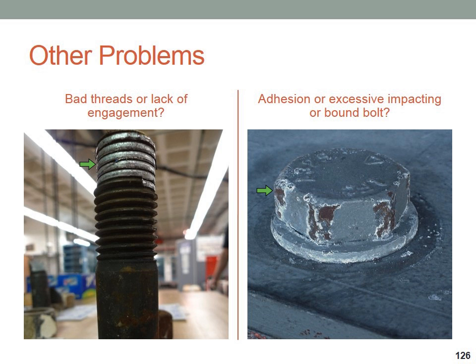One time we had a problem brought to our attention, wondering if the zinc was properly adhering. We actually found out that the zinc had really good adhesion, but in trying to fully tension this bolt from the head side, the connection had slipped so much into bearing that they could not even turn the bolt to generate any tension. It was simply bound up in the steelwork, and through all kinds of ratcheting and hammering away with an impact tool, they basically drove all the coating off of the corners of the threads.